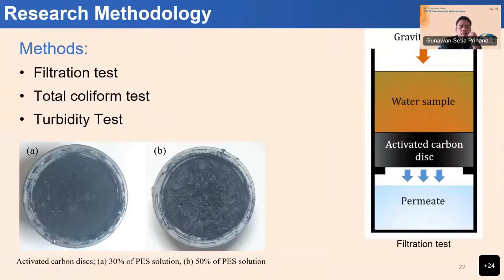So in this research, we conducted three types of tests. First, a filtration test, a total coliform test, and a turbidity test. For the filtration test, we have this small cell. It's almost the same as the cell that we use in the water permeation system, but this one without using nitrogen just to push the water.